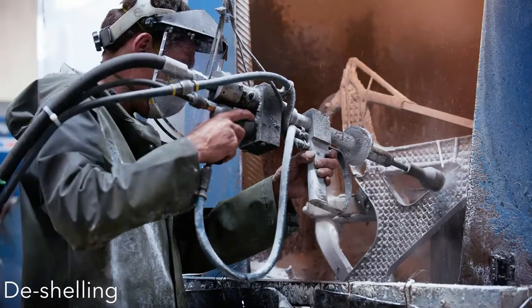Afterwards, once that casting is solidified, it's bead blasted to remove the shell. We have a ceramic shell up here, which you're welcome to come up and take a look at afterwards. It's a relatively fragile material, and after the metal has been poured, it starts to crack. So it's relatively easy to get the shell off using abrasive means like bead blasting.